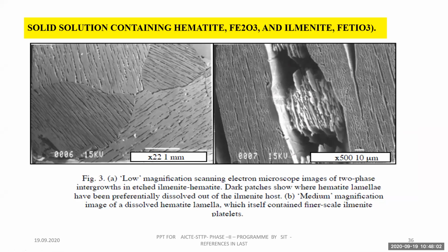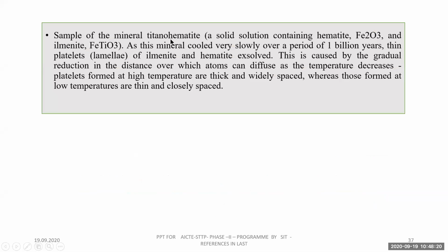The example here: a solid solution containing hematite, iron oxide, and ilmenite, iron titanium oxide, which was formed in olden days. It's a very old rock. A sample of the mineral titanohematite, a solid solution containing hematite, iron oxide, and ilmenite, iron titanium oxide, as this mineral cooled very slowly over a period of 1 billion years, then lamellae formed, that is, ilmenite and hematite exsolution. This is caused by the gradual reduction in distance over which atoms can diffuse as the temperature decreases.